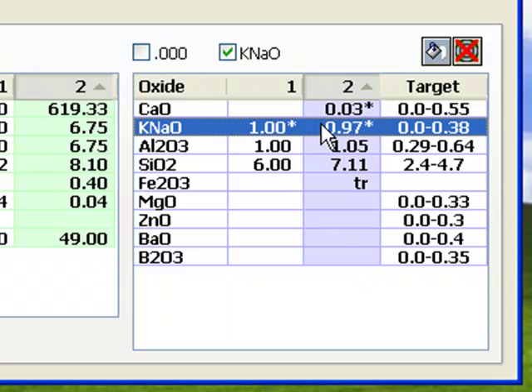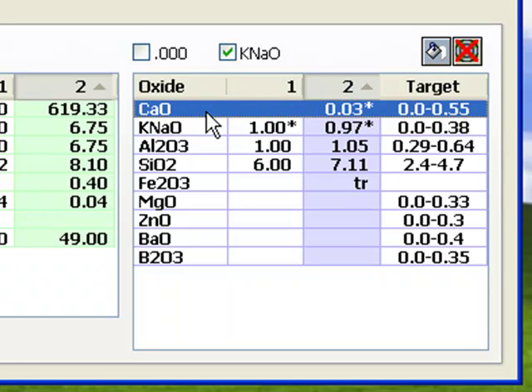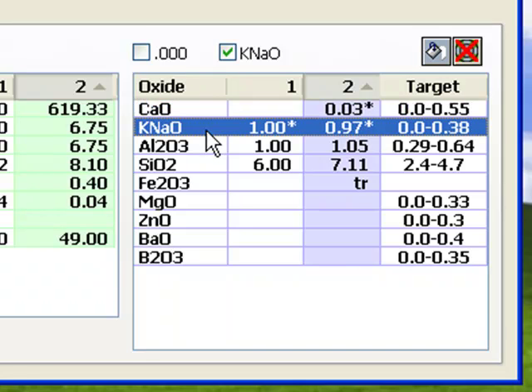By comparing the formulas of the two feldspars with this target, it is evident that feldspar as a glaze is lacking CaO, among other things, and has way too much KNaO. Almost all stoneware glazes have much more CaO than K2O and Na2O to achieve hardness and resistance to leaching, but especially for resistance to crazing.